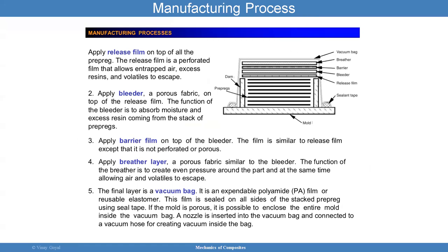So the manufacturing process is as follows. We apply the release film on top of all the prepreg. The release film is a perforated film that allows entrapped air to escape. So that's why we have that there. I'm kind of summarizing, saying it three or four different ways, but I think it's important.